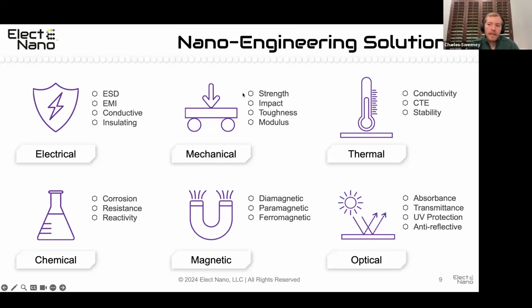Yeah, and so for the underfill application, that was tricky because a single type of functionalization was not appropriate. You could either get stability at room temperature, or we could engineer for stability at high temperature, but it was really hard to get both. And so in that situation, we used a dual functionality to try to split the difference between stability across the entire change in the viscosity and surface energy of that underfill matrix throughout the entire process window.